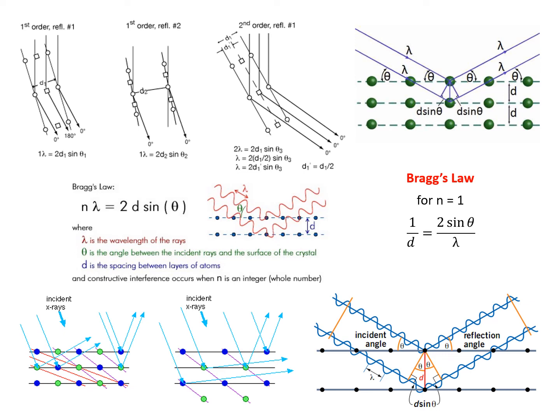But what you'll notice in many texts on X-ray diffraction is that it's often depicted as a plane wave of coherent light, or X-rays in this particular case, coming in, striking atoms, and being scattered away. So the reality is that that's not what is actually happening. What is actually happening is that you're getting light coming in divergent paths and being scattered off and being detected